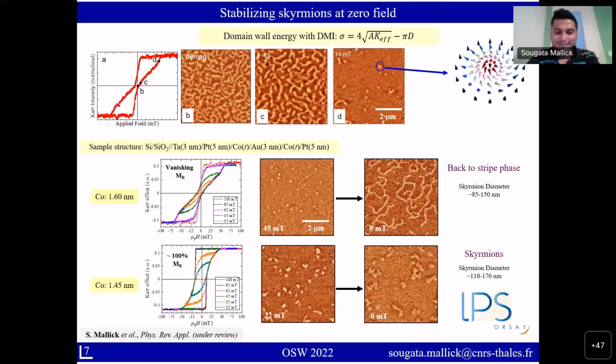This is a very important question, Mudli sir. Actually, it depends on which system you are working on. If you are working with ferromagnetic samples, you can use a conventional soft magnetic tip, like 7 to 10 nanometer of cobalt with a capping layer of 20 nanometer of aluminum or something. When you are working with synthetic antiferromagnets, the exchange coupling between the two lattices is so large that you cannot perturb those textures, so you can take a very high moment magnetic tip. What we usually do is take 40 or 50 nanometer thick cobalt tips.